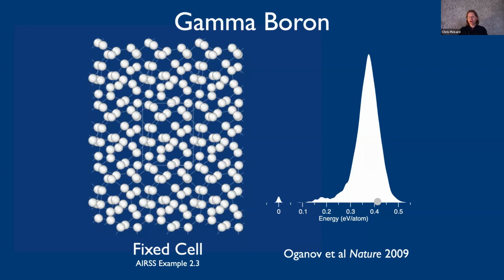So if we multiple times randomly put atoms in a box and do a local geometry optimization using CASTEP, most often you'll end up in this peak of the structural density of states that you see on the right-hand side. Zero is the ground state structure, and about 0.4 eV above the ground state is where most of your structures end up. The key thing is they don't all end up in these high energy states. Sometimes, about 1 in 200 times, they end up in this low energy state. So this is what it looks like if you do a geometry optimization from this random structure, and we're going to end up where this gray spot is, about 0.4 eV above the ground state.